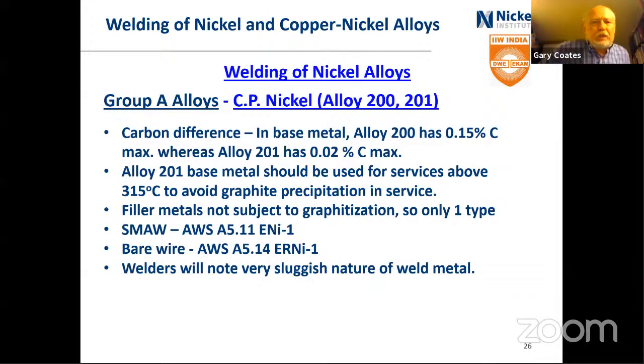So when we talk about the commercially pure nickel, when it comes to the base metal, there are 2 different types. There's the 200 alloy, which has a relatively high carbon content, and the 201 that has a low carbon content. And the 201 base metal is used where you have a service that goes above 315 degrees C, because the carbon will get together and form essentially graphite at the grain boundaries, and then that's a problem with end use. It corrodes rapidly there. However, the filler metals are not subject to graphitization, so there's really only one type of filler metal used for both 200 and 201.